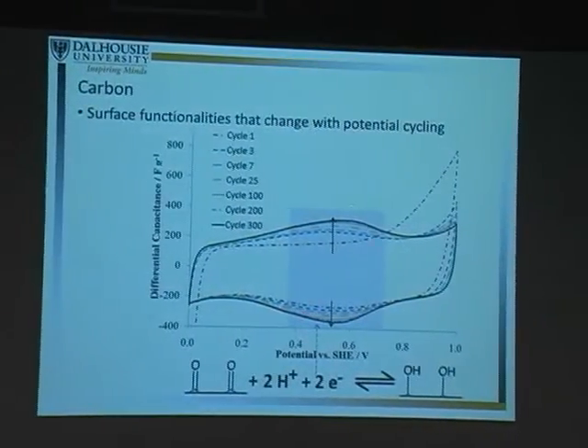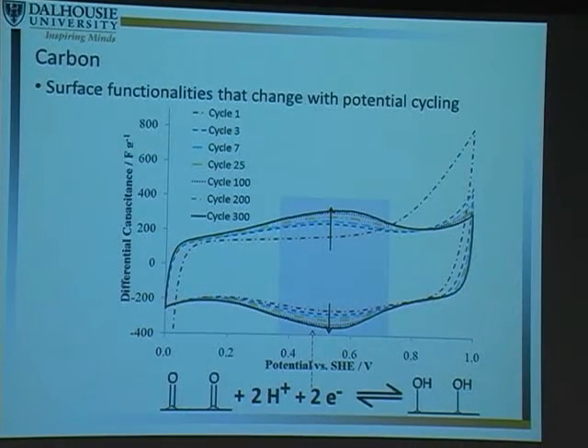And this is the one that is believed to be reacting right here at 0.5 volts versus SHE. And again, this is the one that we can develop through cycling, one of the reasons that we picked this particular carbon. So we know this quinone peak develops. We know that we want it to develop, but how does it develop? Where does it come from? It's either on the surface but not active, or we are actually making this carbon surface functionality in our treatment of the carbon. And so we wanted to find out where it comes from, because again, it's the surface functionality we'd like to increase on the surface.